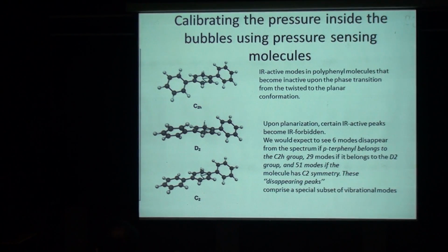How do we measure the pressure inside a nanobubble? Is there any physics instrument that has such high sensitivity, allowing us to probe the pressure inside? As I'm not a physicist, I do not know how to use an instrument to measure the pressure, but we can use chemical molecules to calibrate the pressure. Some chemical molecules are twisted. You see this carbon ring, this 6-membered ring, they are sort of twisted. It is known by theoretical consideration that if you want to bend the ring and make it flat, you need a certain pressure. This pressure can be as high as megapascal or gigapascal.